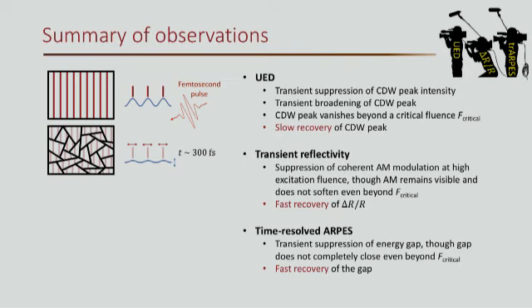So how does this explain the observations? First of all, due to the suppression of amplitude and the excitation of the phase mode, there's a suppression of the CDW peak intensity. And of course, the formation of small domains explains the broadening effect from the loss of long-range order. Beyond the critical fluence, this huge fluctuation of the phase, the suppression of intensity, as well as the formation of domains will drive the intensity of the CDW peak below our detection limit. That's why it seems that it basically vanishes.